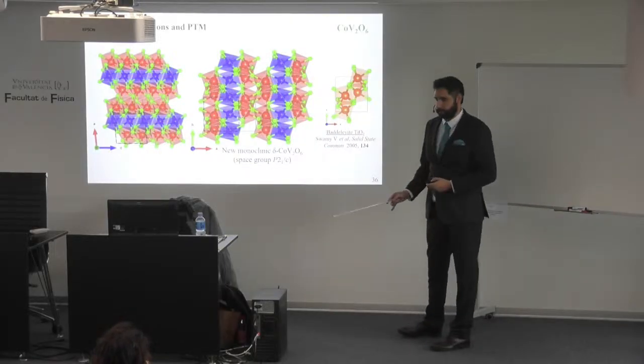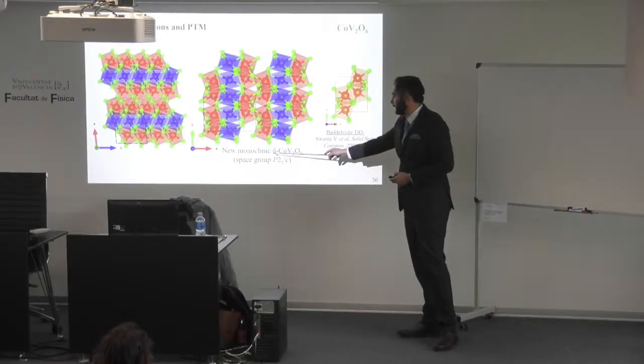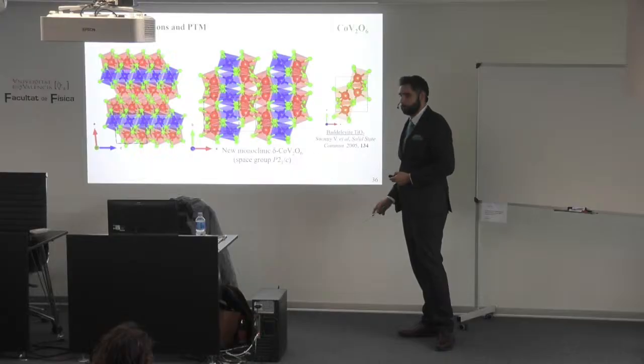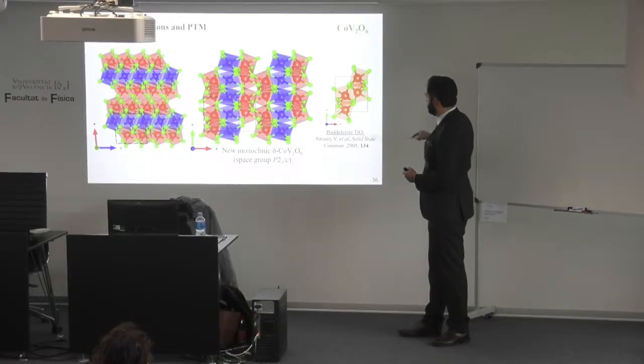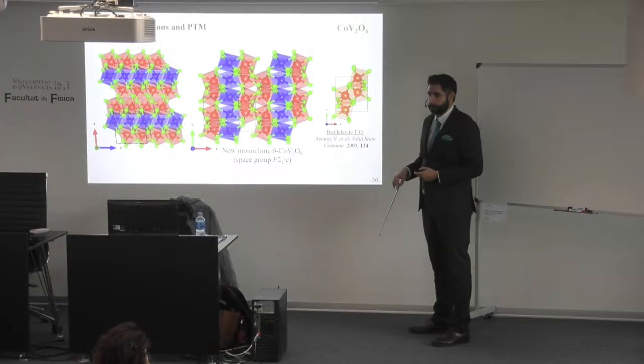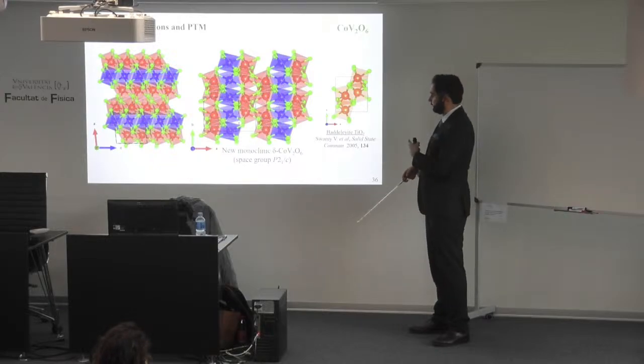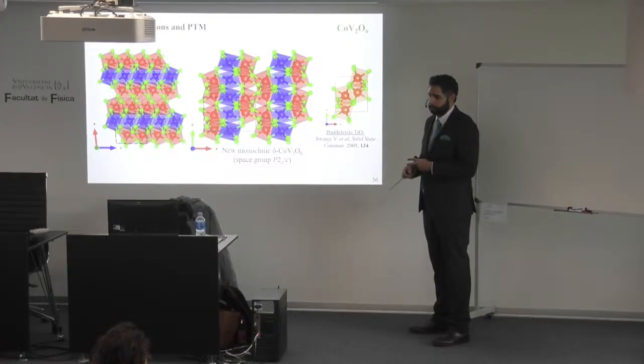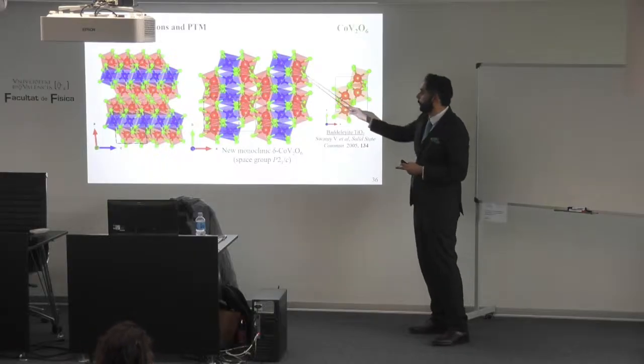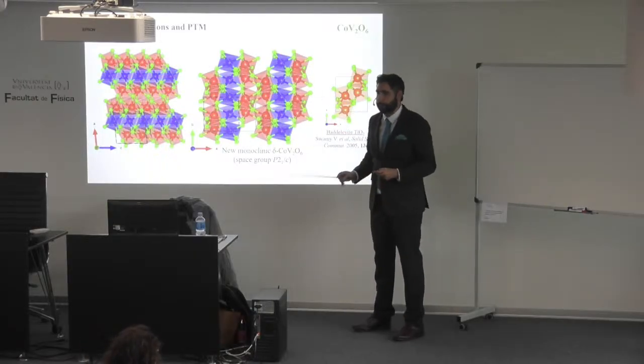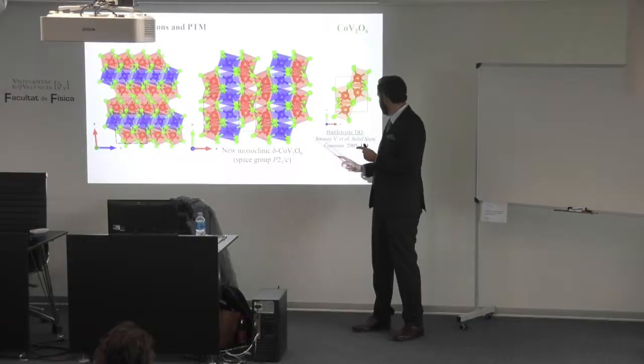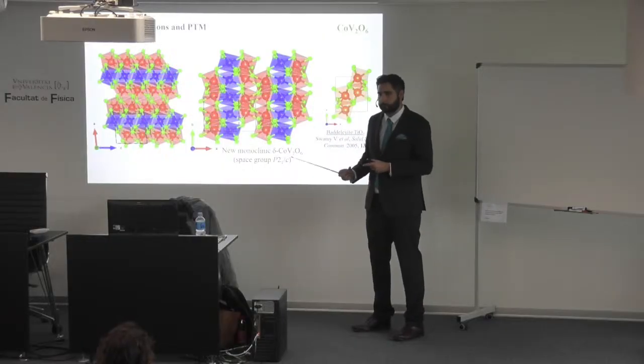This is the last structure. This is a monoclinic new structure for cobalt vanadate, and this phase transition was also seen for titanium oxide. In this case, they synthesized it directly at 32 GPa and 800-900 Kelvin in order to get this sample. We got it just with pressure, but the columbite to baddeleyite phase transition was also seen for us.